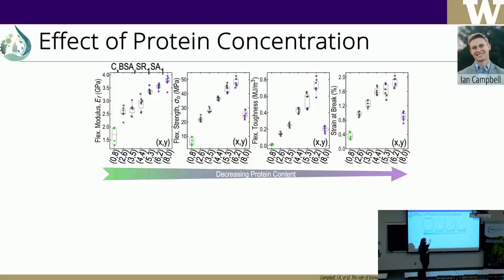But we haven't actually identified what is the sweet spot or a maximum, because you see that the last point is a 20%, 2 to 8 by weight protein to cellulose. I actually think you don't need that much. I think you would go higher if you have less amount of protein in that particular composition. But this is just to scan effectively the space. It's not to identify the maximum.